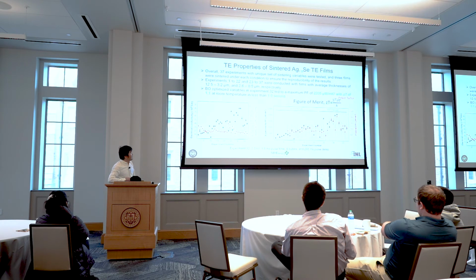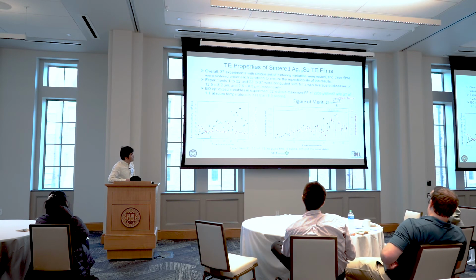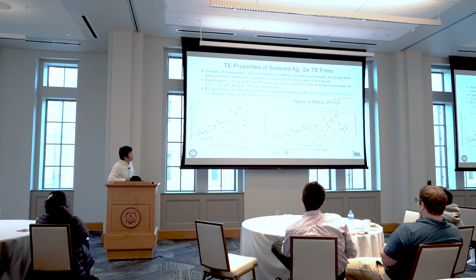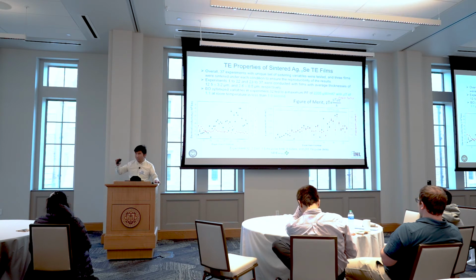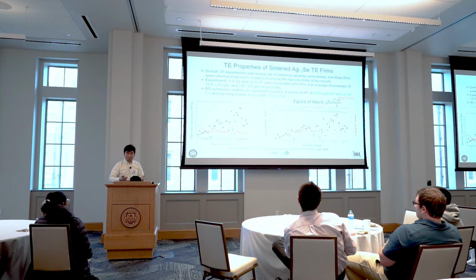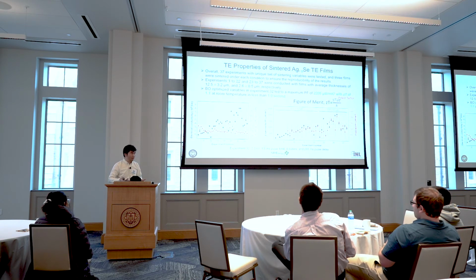And then eventually we're able to get a power factor over 2200 with a ZT of 1.1. And this is the best you can find in the literature. And it was not based on the trial and error method other people usually use. It's a more systematic, data-driven, AI-guided method. And we're able to beat whatever reported results are out there. The paper is under review.